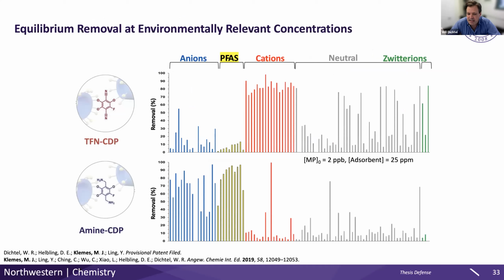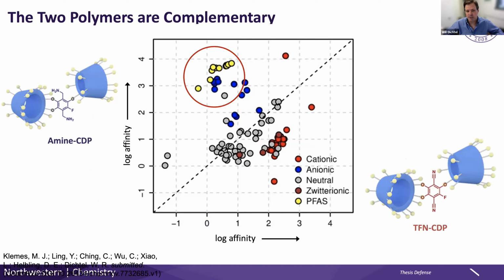And indeed, when we did that change, the selectivity of the material reversed almost completely. And so we did the same panel of pollutants in collaboration with Damien Helbling. And now we see most of the cations don't bind well. I have no explanation for this one that still does, but it's certainly an outlier. And then all of a sudden, most anions start to have a very good affinity for the material. And we were delighted to see that among the anions, these anionic PFAS compounds of various sizes were among the strongest binders to this polymer. And so this is kind of another way to look at that complementary selectivity.